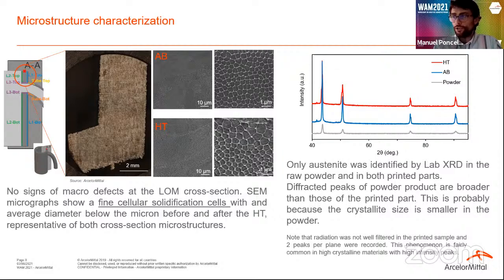And looking closely at the microstructure by SEM images, we saw a very fine microstructure with fine cellular solidification cells with average diameter below the micron, so very fine. And also this microstructure was preserved after the heat treatment, which is good, it is what we intended. We measured this cross section by lab XRD, on both samples, and also powder from the same printing batch, and we saw that this is a mainly austenitic phase, which is not surprising, as this steel is very well known to be mainly austenitic. So this is also an important input for measuring the residual stresses, to know initially the microstructure that we have.